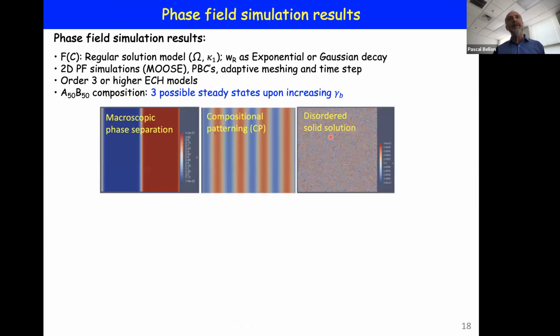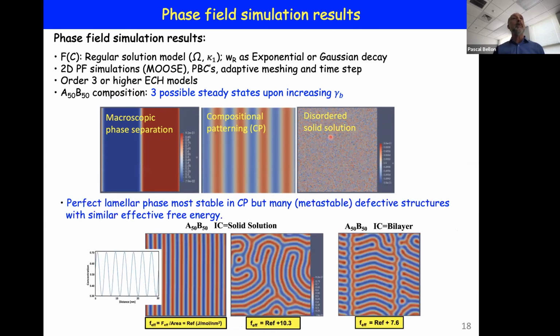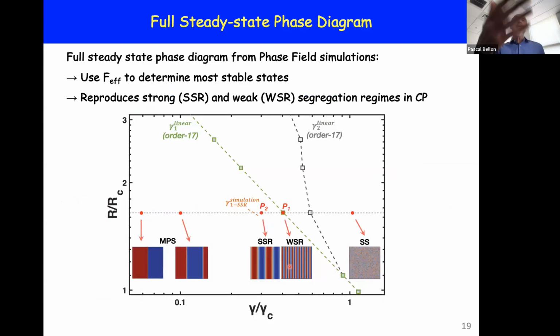So I don't want to spend too much time on details because I think it's a little bit beside the point of this seminar. But we use phase field modeling in MOOSE, this open platform that's been developed at Idaho National Lab, to solve this phase field model. Here's the kind of microstructures we see for macroscopic phase separation, compositional patterning, or a disordered solid solution. Since we have an effective free energy, even when we have metastable states, we can decide which one is the most stable. And we built, in somewhat great depth, this steady state phase diagram that I mentioned earlier. And you recognize here in the middle this region for self-organization or compositional patterning.